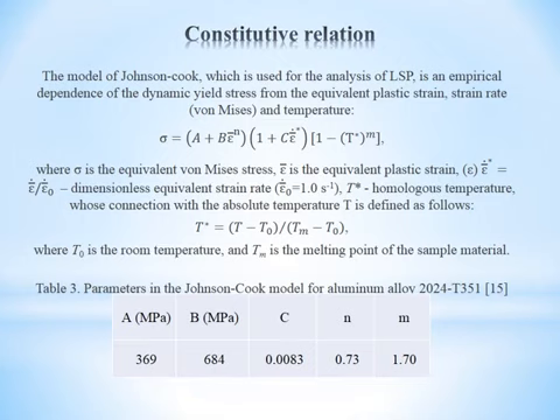The Johnson-Cook model, which is used for the analysis of LSP, is an empirical dependence of the dynamic yield stress on the equivalent plastic strain, strain rate, and temperature. The equation contains 5 material constants which are determined empirically: A is the static yield stress, B is the modulus of strain hardening, N is the exponent in the law of strain hardening, C is the coefficient of the strain rate, M is the exponent in the law of temperature softening.